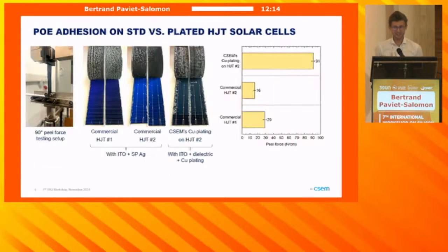A second advantage of our process is that it features pretty good adhesion with the POE foil. To illustrate that, I'm comparing on this slide the peel force testing on different heterojunction cells. We took first two commercial heterojunction devices. They have standard ITO and standard screen-printed silver at the front. And for those, the peel force appeared to be pretty low, around 30 or 16 Newton per centimeter, whereas on